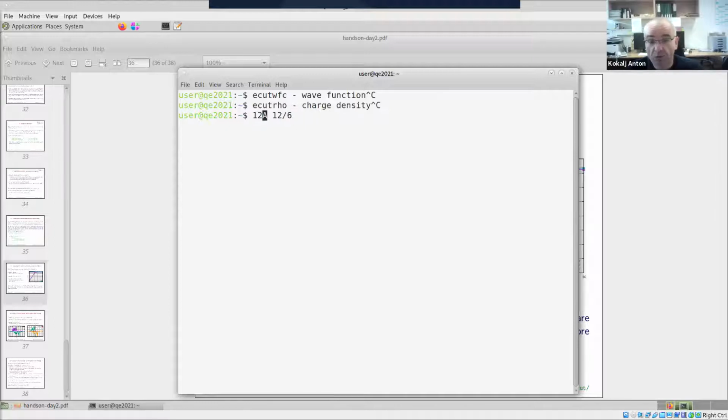But if I do a 12 by 12 by 12 supercell, then at this point, because I saw that, for example, for aluminum a 12 by 12 by 12 K mesh is enough, if my supercell is 12 by 12 by 12, this implies that I can easily take a single K point and I will be at the same precision as for the unit cell when I use a 12 by 12 by 12 K mesh.